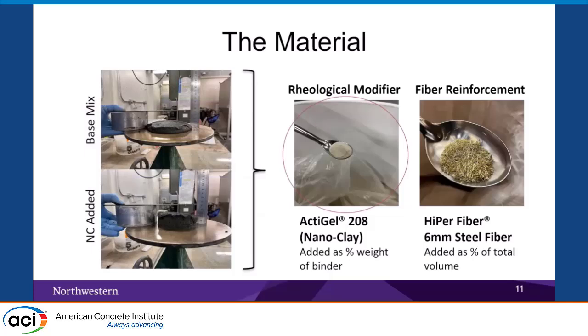When we use this nanoclay, we can see the difference in the slump height for the base mix and after using nanoclay. The slump table test is a good tool to judge if this mix is going to be printable or not. However, it's a simple tool. We have also done several good works in rheological characterization of this mix using different rheometers, but this is out of the scope of this presentation. So I'm just showing the slump table test for reference.